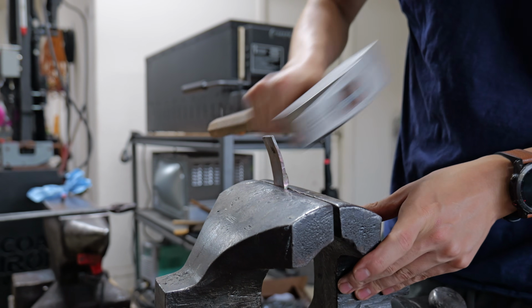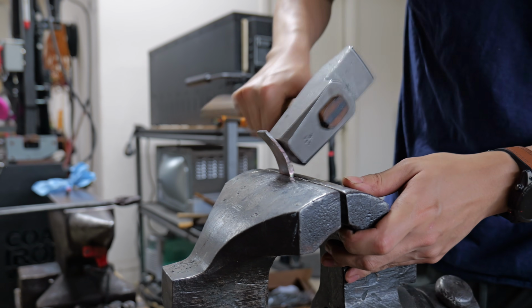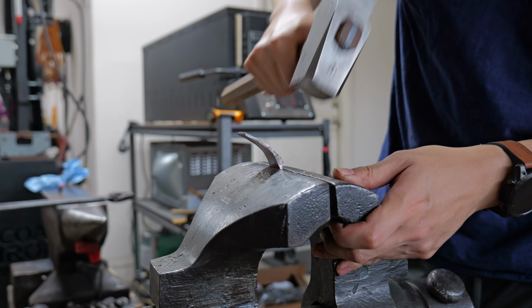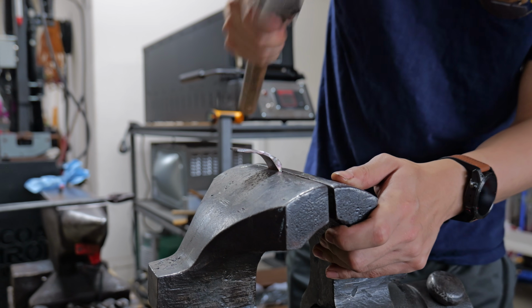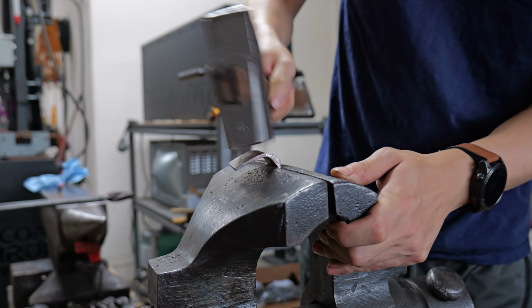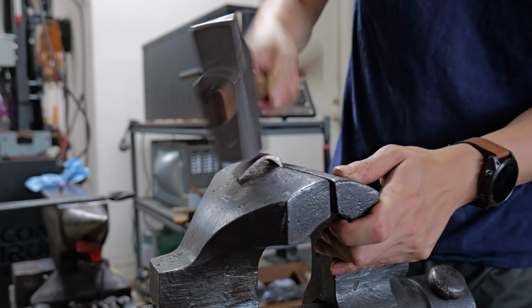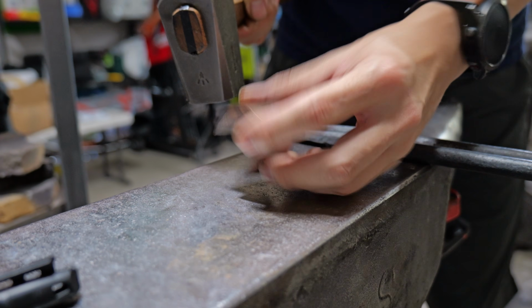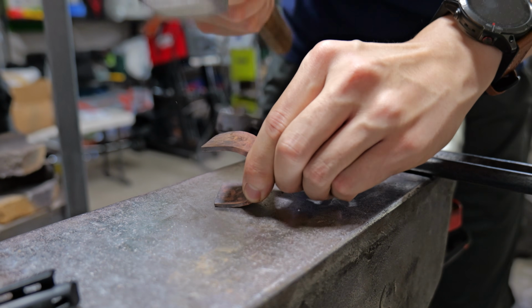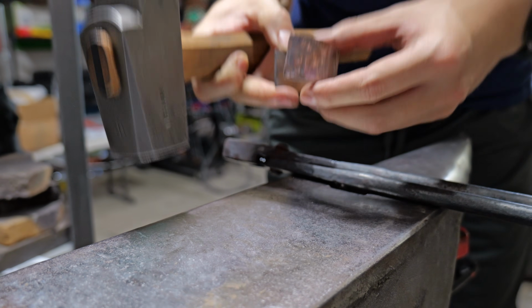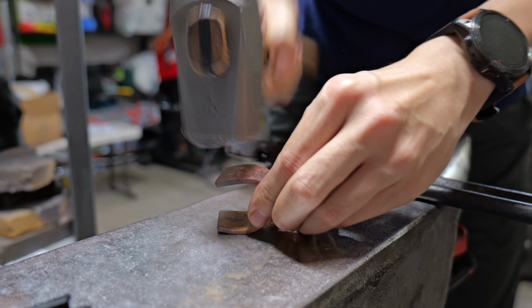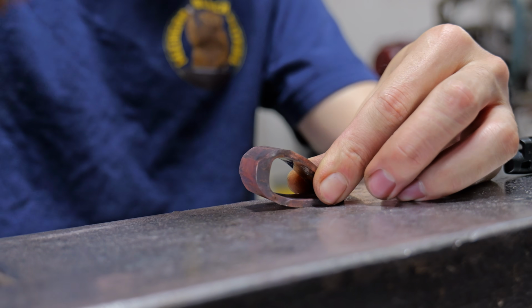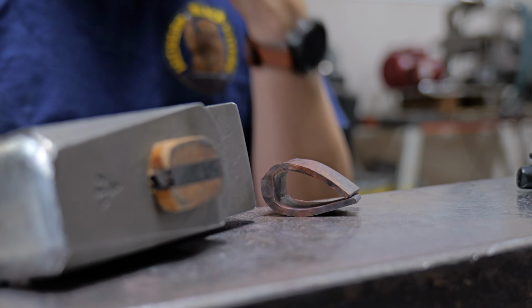Now that the copper was at an adequate thickness, it was time to take it over to the post vise and begin bending it into that deep U shape. This is super tricky because that thick part in the center has to stay in the center. It has to be behind the spine of the blade. The copper at this point was pretty springy. I might not have annealed it correctly the cycle before, and so this step right here was a lot more difficult than it should have been.